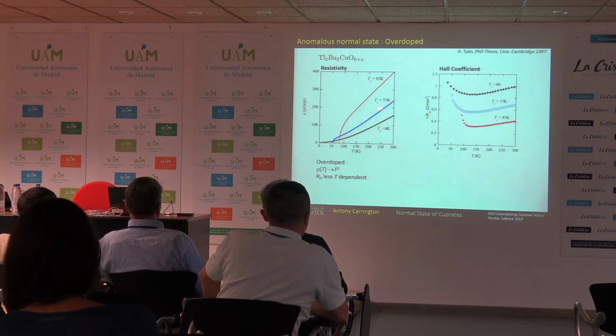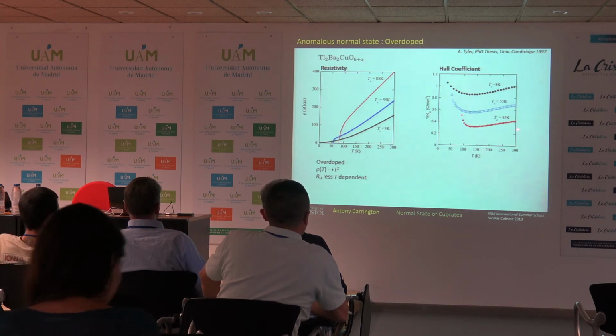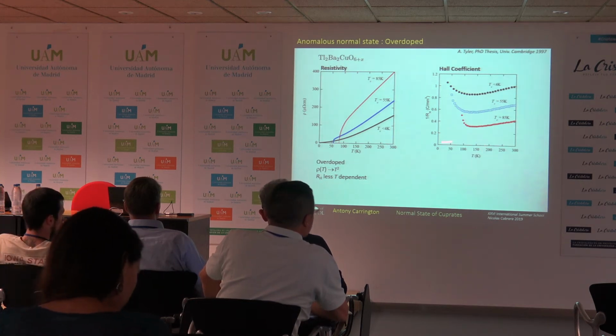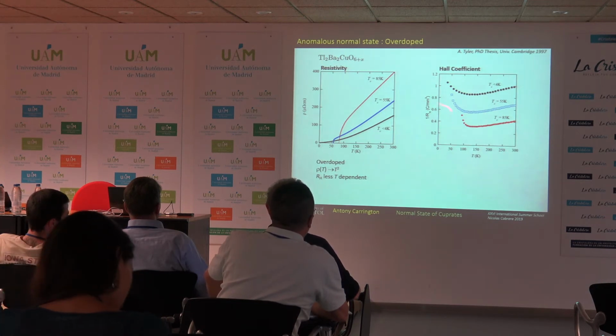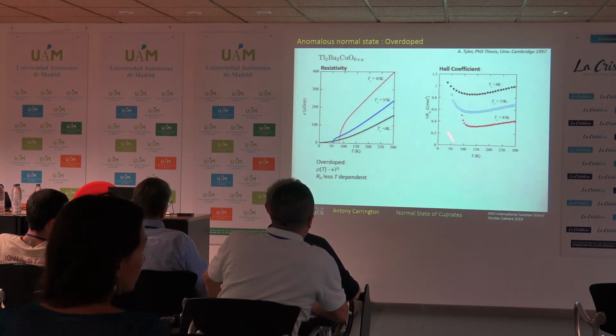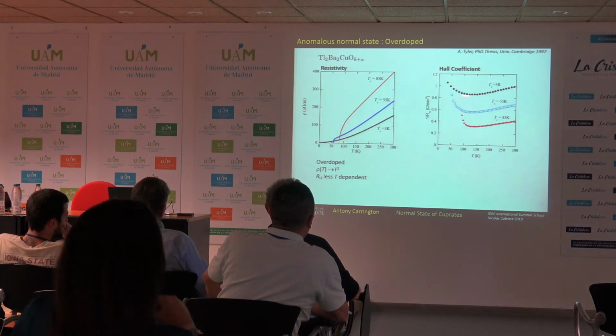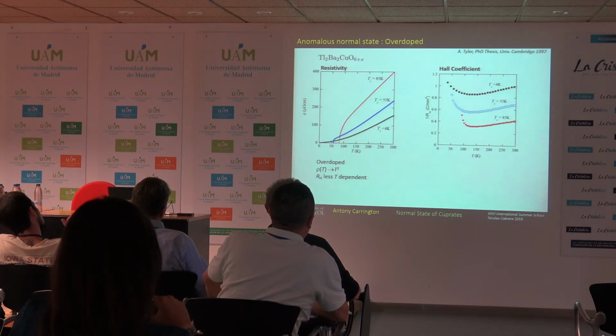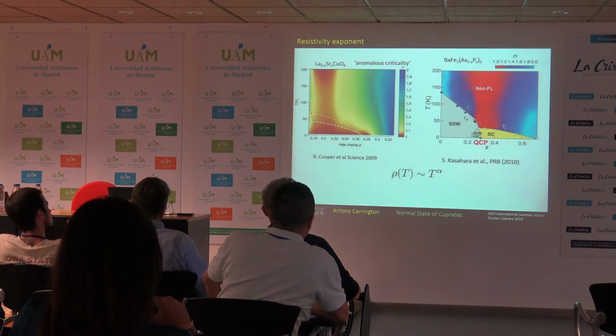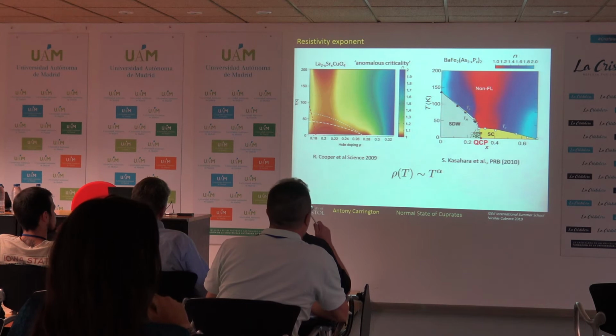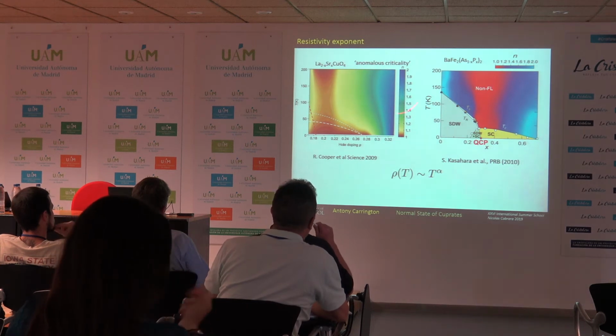The Hall coefficient, on the other hand, starts off being approximately linear with temperature, 1 over RH, and then as you get more and more overdoped, the temperature dependence becomes weaker and weaker. So here it's only varying by about 10% over the full temperature range. Okay, so if we focus now on the resistivity,